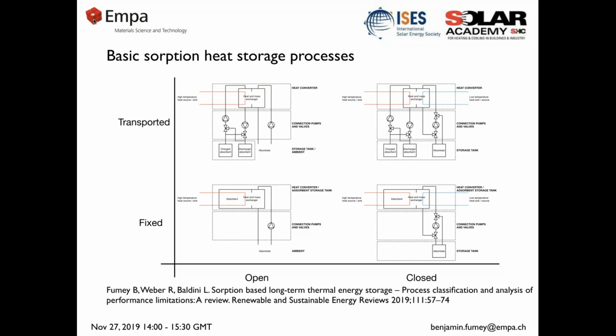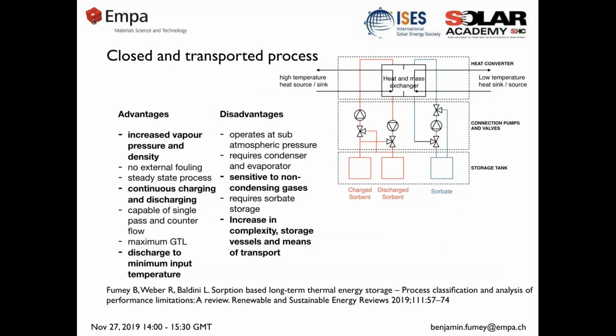and further details would be found in the publication mentioned below. Just a brief point to make is that we do find that the closed transported system has some benefits over the others, with closed having a higher vapor pressure and thus a better discharging performance, and transported being able to cool down the absorbent further, especially if there's a counterflow process between the heat transport fluid and the sorbent, and thus being able to discharge better. So we already see that the choice of system process does have an effect on the performance of the material.